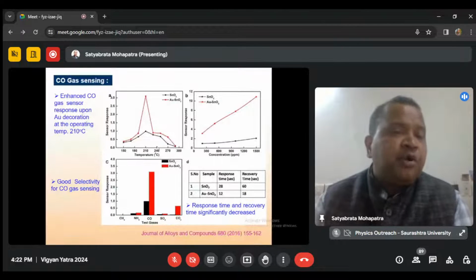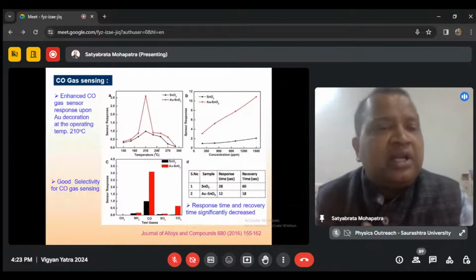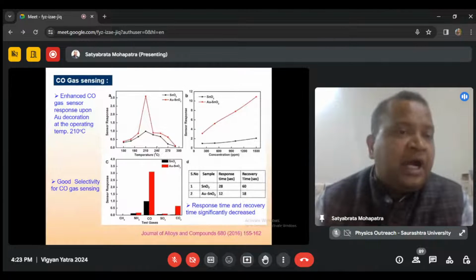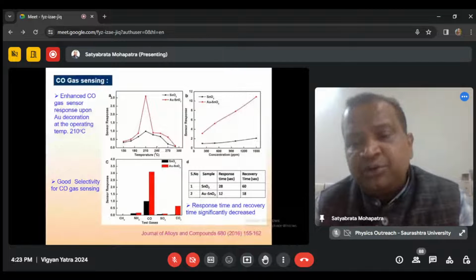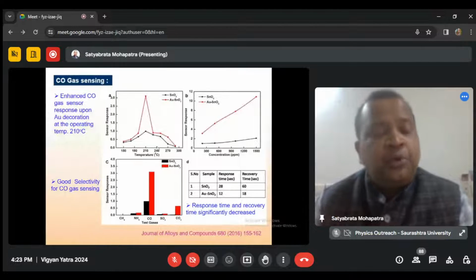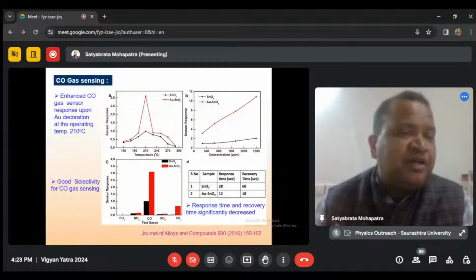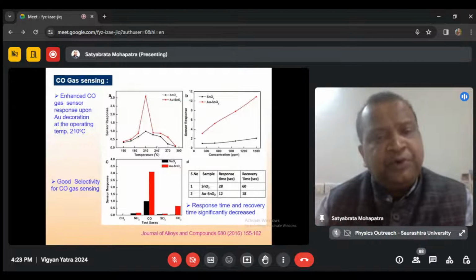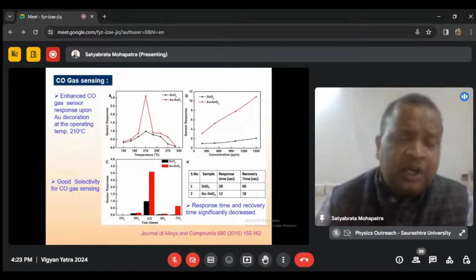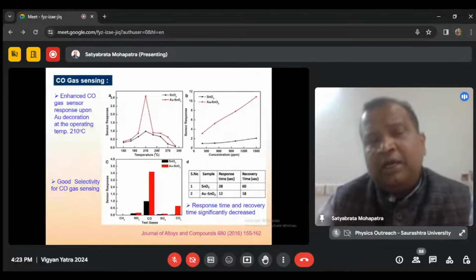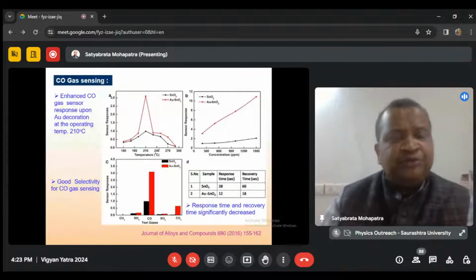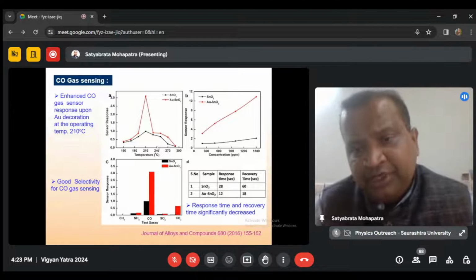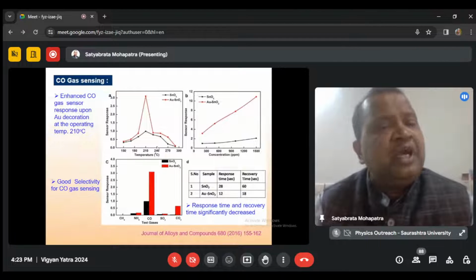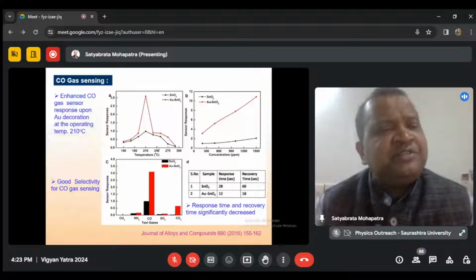Now, what is important here, we wanted to see whether gold nanoparticle decoration can improve the carbon monoxide gas sensing response. We are exploring various approaches which are beneficial in the development of strong gas sensors. It should be simple, like depositing a very small 5 nanometer film of, let's say, gold or silver, and in this case gold, and if you can show a very strong gas sensing response, that's very easy to make, and it's scalable as well. You can go for a large area coating by this very simple technique.